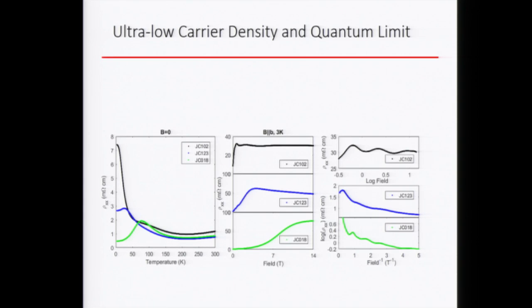So here, this is a resistance plot in log B, right? You start to see some very weird behavior in the ultra quantum limit, where the magnetoresistance actually oscillates as a function of log B rather than 1 over B.